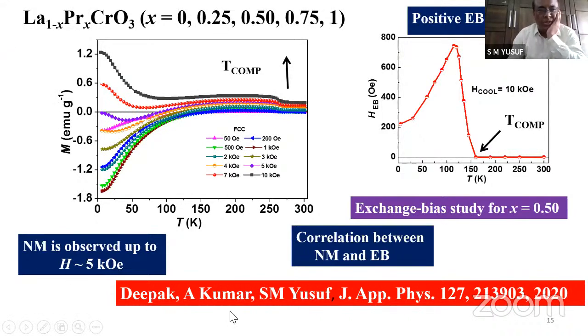Another system which we again work with is for Deepak. Professor Suresh is attending. In fact, he is one of the doctoral committee members of this student. And so here, what you see, magnetization as a function of temperature, and you see how this magnetization is negative, but at higher field, not very high, it becomes positive. So this kind of reversal is possible even with a small applied field. So here there are two things: temperature dependent magnetization reversal, as well as field induced magnetization polarity reversal. Both you see. But one point I would like to bring to your attention here is the exchange bias, as a function of temperature, of course, here we use a 1 Tesla cooling field.